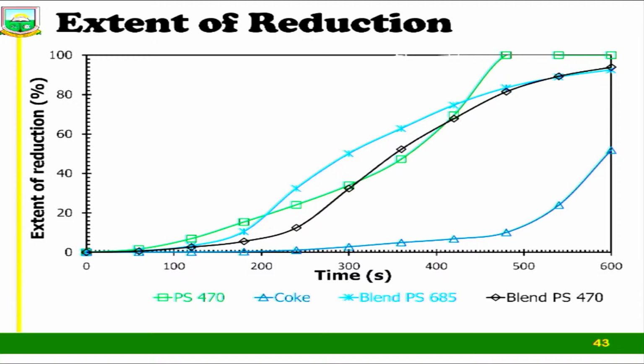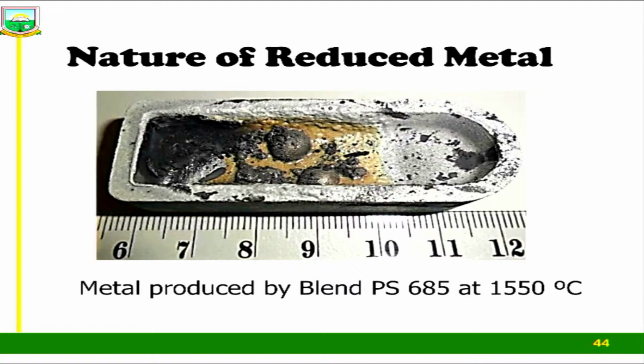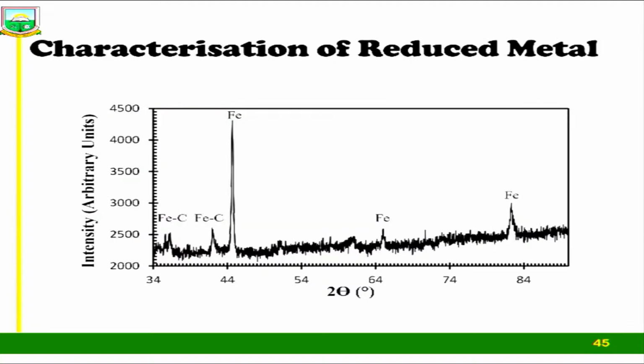PS 470, which is a blend of the polystyrene, had already gone to completion, and the rest were at a very high extent of reduction. That is what we got after the reduction process. This is EAF slag, so you don't expect to, but the metals are there. You can see those spheres over there. And then when we characterized, we saw that we produced predominantly iron at the peaks 45, 65, and 82 degrees for the 2 theta. We also had some carburized iron at around 35 and then 43 degrees. Those are the typical conditions for metallic iron and carburized iron.